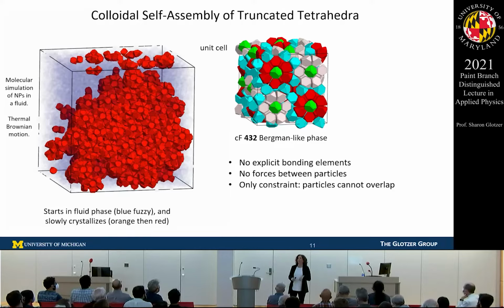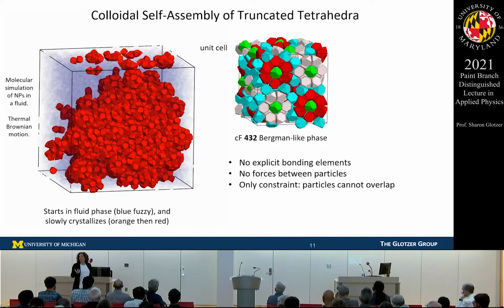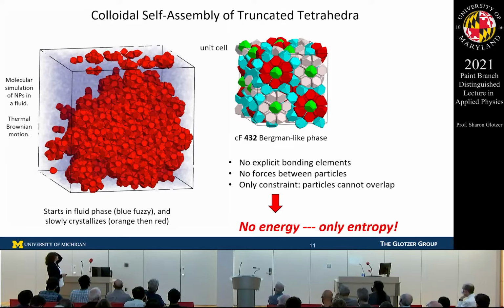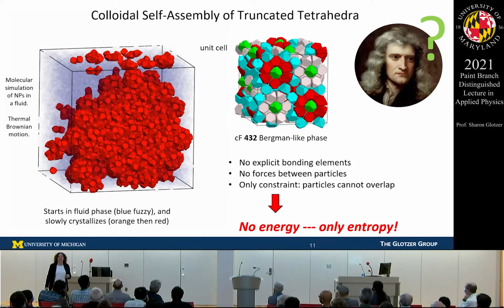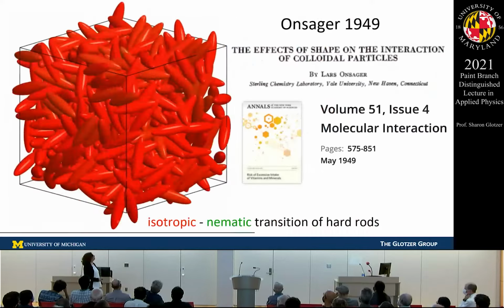The box has periodic boundary conditions, but you can see here that it forms a coexistence of this really complicated crystal and a fluid phase. Okay, but there are no interactions, so there's no energy. The only thing you have in this system is entropy. So this system went from a disordered state to an ordered state, and there's nothing in the system but entropy. So what would Newton say about that if he looked at that crystal forming? If I showed you that movie and I didn't mention that there weren't attractive interactions, you'd probably think there were attractive interactions between them. Otherwise, how else would they come together like that? So that's what we're going to spend our time talking about.